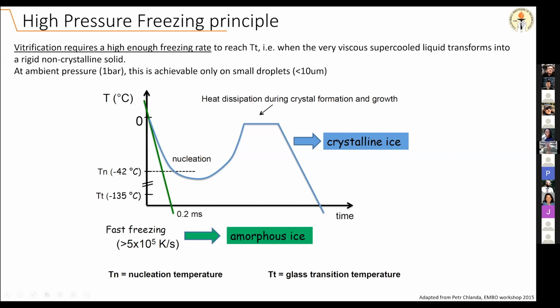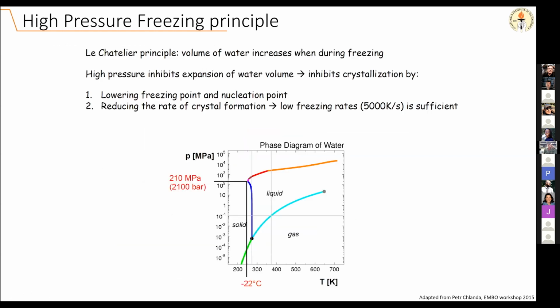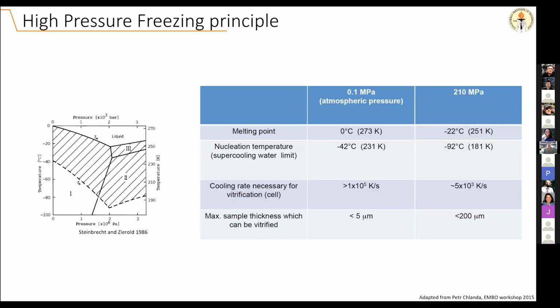But when we want to do it on thicker samples, we need to increase the pressure. So by increasing the pressure, what happens is that we inhibit crystallization. And so by doing this, we lower the freezing point and the nucleation point of water, and this reduces the rate of crystal formation. And so that allows us to freeze or to vitrify samples that are below or equal to 200 microns in thickness.